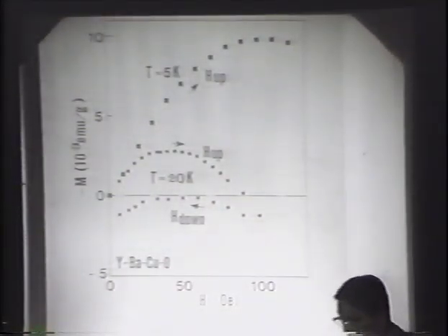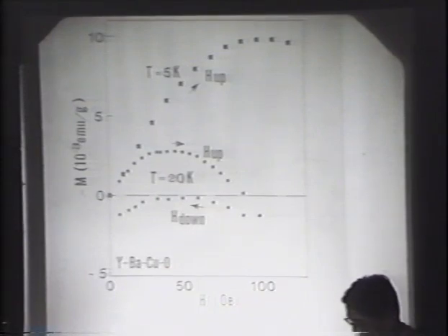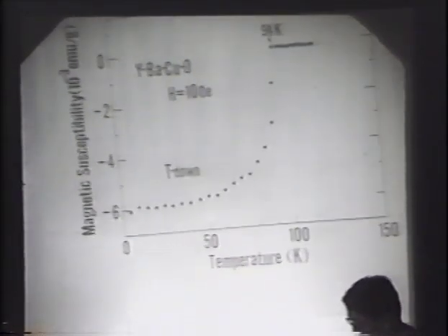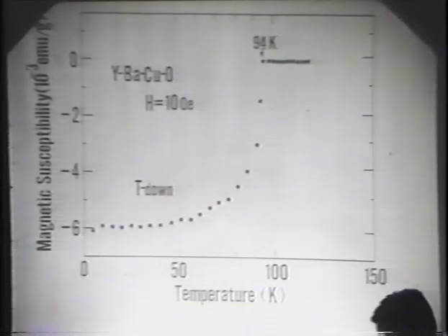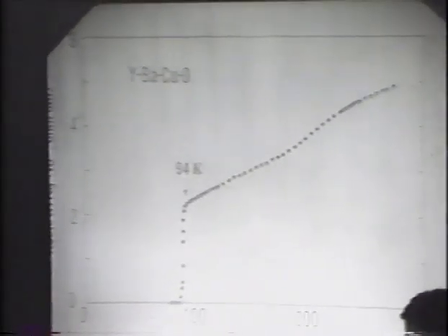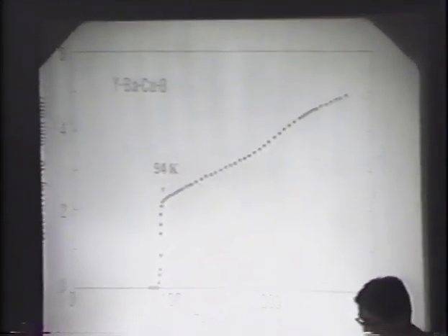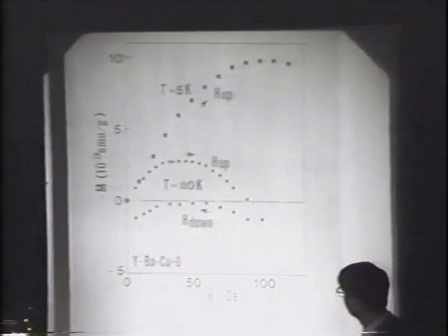We succeeded also in making yttrium barium copper oxide of almost single phase. As you can see in this graph, the Meissner effect reaches up to 50%, and the shielding effect signal reaches up to 150%. The rise of the diamagnetic signal is quite sharp at 94 degrees Kelvin. The resistivity also drops fairly sharply at 94 degrees Kelvin. HC1 is almost 100 Oe at 5 degrees Kelvin.